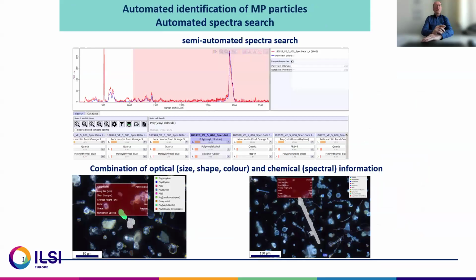Here it is shown that you can very easily do a spectral search, and the program automatically identifies the particle. In this case, it is a PVC particle. And then you can combine all the optical information, the size of the particle, the shape, with the chemical information. We can also identify fibers, and you can bring this then to a database. At the end, you have for every sample the numbers of particles, for example, here 77 polypropylene in the sample, and also the particle size distribution for every polymer. And if you want, you can go to every piece of information for every particle.